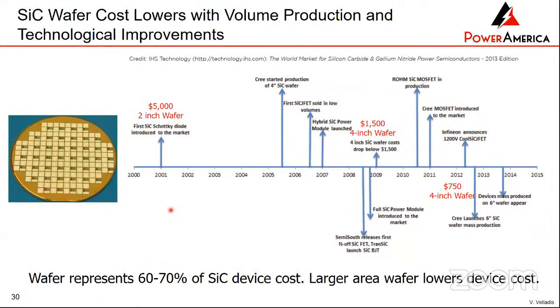And if you look at the wafer cost, back in 2001, a 2-inch wafer was $5,000. And with years of production, with technology improvement and larger volume production, we've come now to having 6-inch silicon carbide wafers in production, and the cost is about $600, $700. So the price has gone down substantially from the old days where very small wafers would cost a big amount of money. However, the cost is far more expensive than the cost of silicon. Silicon wafers are about $20 a piece. With silicon carbide, it can be $600 and maybe a little lower in volume production.